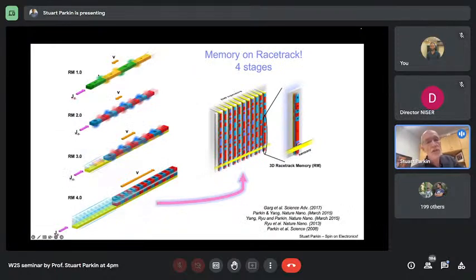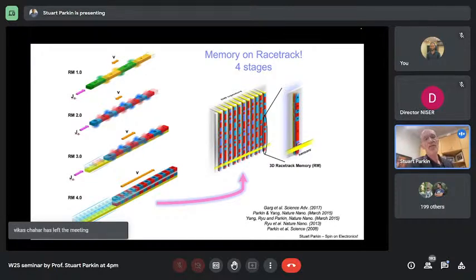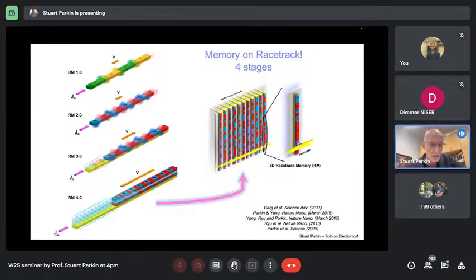However, I call this racetrack memory 1.0 because the domain walls in soft materials can be very, very large. In fact, they're not well defined. They can expand if there's defects or for some other reason. They can become microns long, even though they might be initially a few hundred nanometers in size. So this doesn't work technologically, although we did demonstrate the motion under current of a series of domain walls in the same direction.